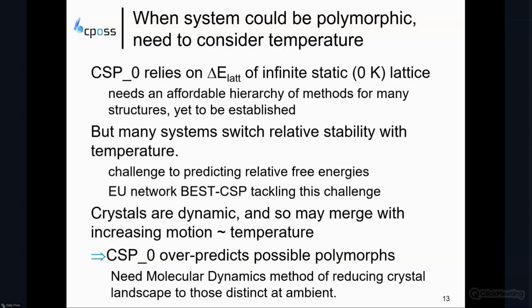And it may be that some parts of your molecule go into free rotations like methyl groups or large groups. And one of the reasons why we get so many more lattice energy minima than possible polymorphs is that for some of the structures, the barriers between them are so low that they will merge as you increase the temperature, or they will have merged by the sort of temperatures that you reach in crystallization. So we need a method that models how the crystals are actually moving to reduce our crystal energy landscape to the minima that will be distinct structures at ambient or practical temperatures, not at 0 Kelvin.